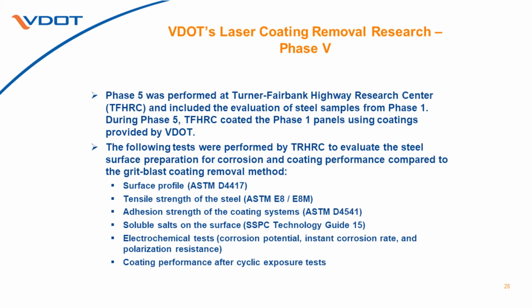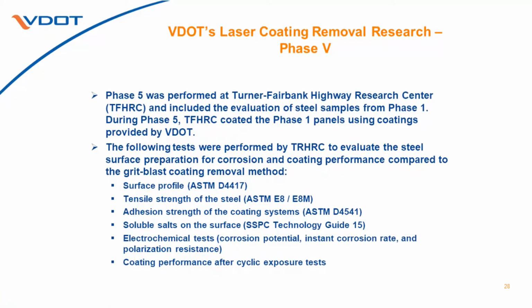Phase five was performed at the FHWA Turner-Fairbank Lab in Northern Virginia. And the idea of this was to perform some testing on the samples that were cleaned during phase one. So the following tests were performed to evaluate the steel surface prepared for corrosion and coating performance compared to a grit blasted surface. So we're trying to compare the laser cleaned surface to abrasive blasted surface.